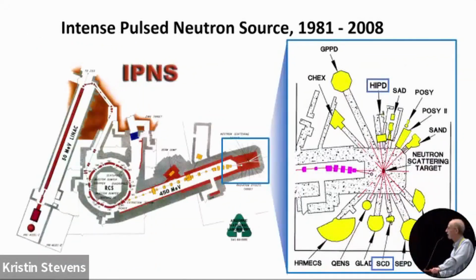So here's a schematic diagram of the Intense Pulsed Neutron Source. They start out with H- particles, which are accelerated in the LINAC here, turned around and injected into the rapid cycling synchrotron. And when they're injected, the electrons are removed by passing them through a thin charged graphite film. And so now we have protons accelerated in the RCS. This source ran at 30 hertz. So 30 times a second, a pulse of protons would come down the beam line to the neutron scattering target, which at IPNS consisted of depleted uranium. And then surrounding that are various moderators and the instruments.